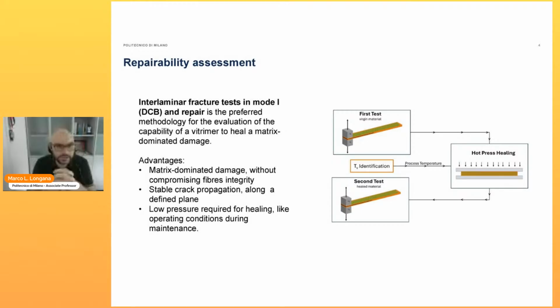A standard, of course, doesn't exist yet. One of the targets would be at least to propose a repeatable and coded standardized way to assess the repairability of a vitrimer matrix composite. We're doing this using a double cantilever beam test, which substantially allows a crack to propagate in mode 1. In this way, we are substantially damaging only the matrix, and we are not compromising the fiber integrity.